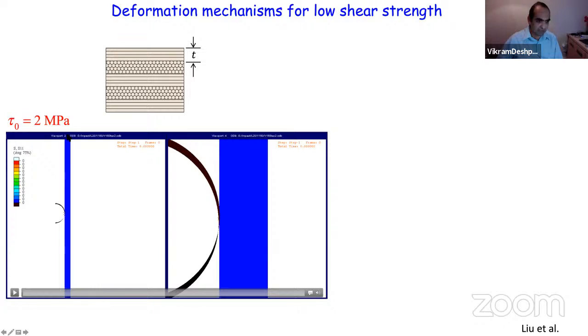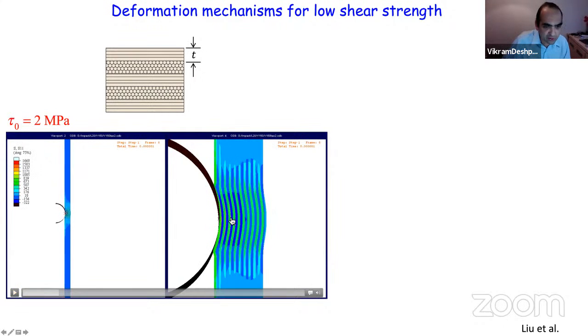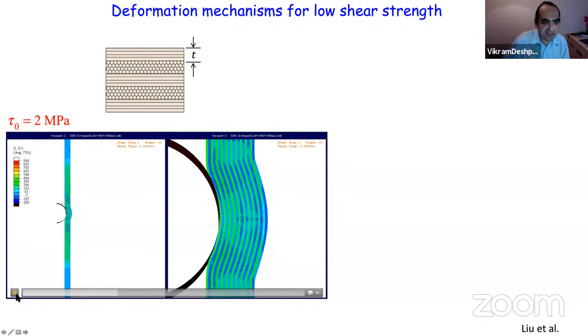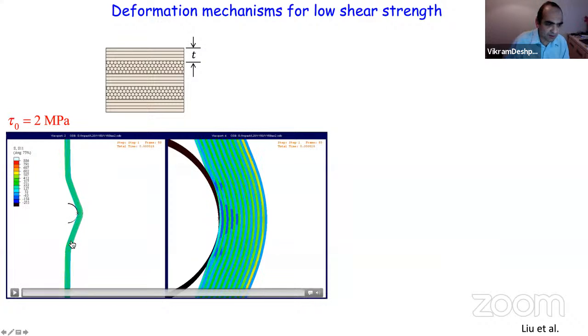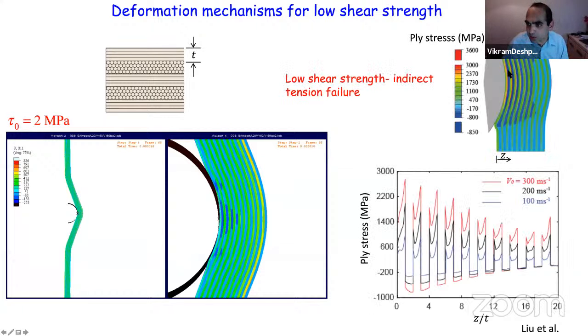So this is an infinitely long beam, and there's a spherical projectile that's coming and impacting this plate. This is a zoom up from here, and you can see that immediately underneath the projectile, you've developed very high stresses. As you go further in time, these stresses just relax, and in fact they keep reducing, and then you just get a propagation of a shear hinge for a very low shear strength beam. You get these very high stresses very early, which are what break those fibers. And if they don't break there, then you're not going to get failure.